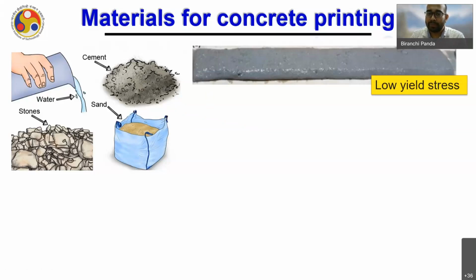But if you use a low viscosity material, once you deposit it, because of the low viscosity, it is going to spread away easily on the print board. This is again not required in our concrete printing application, because we always want the material to remain in the same shape as the nozzle. Suppose we are using a square nozzle or cylindrical nozzle, the filament that we are depositing on the print bed should retain its shape as it is. If it is flowing or spreading away, it means the material is very poorly designed, or it's a very bad material for concrete printing.